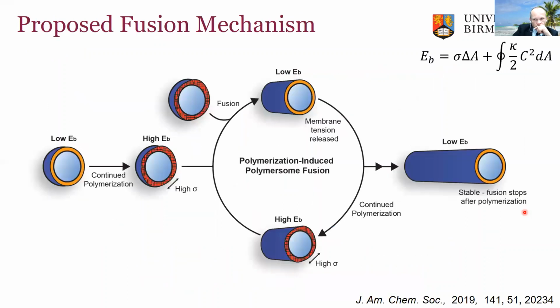So as I said, our proposed mechanism is that we have these low tension polymersomes. The polymerization proceeds very quickly and builds up tension quite quickly, so we have a very high energy of bending, and fusion helps release that. But then as polymerization continues, we build up the tension again and high energy of bending, and again a cycle of building and releasing tension allows for growth of our tubosomes. These tubosomes that we form are stable, and fusion stops after the polymerization stops.